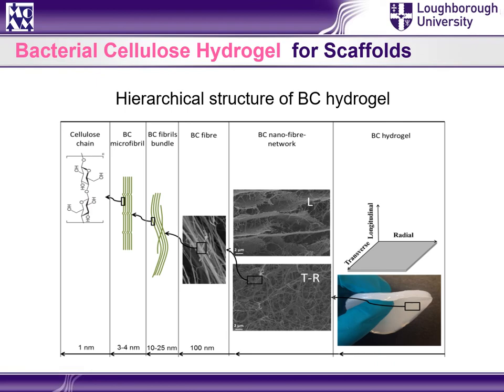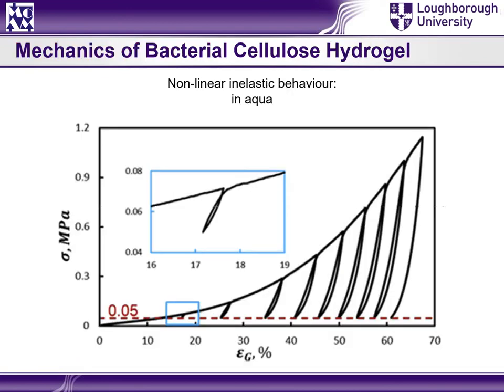This is the hierarchical structure of these hydrogels. You can see that it starts at the level of nanometers, going all the way to the macro scale, and the wet specimen here has features not dissimilar from polymers. Still, to remind you, it doesn't have a polymeric matrix but a water one, with 98 to 99 percent and more of water content. As a result of such a complex microstructure, hydrogels present a rather complex deformational mechanical behavior, as shown in this slide for their test in water.